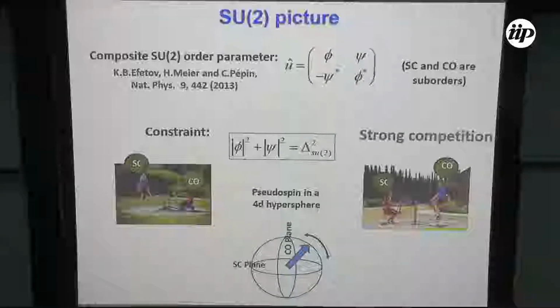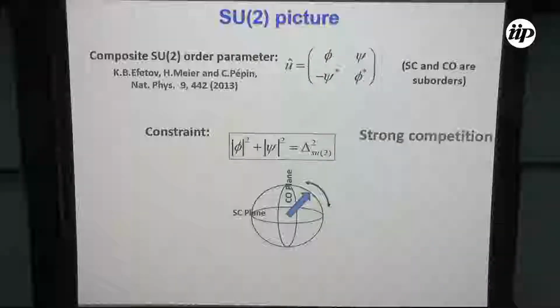We can represent this constraint by a pseudo-spin which lies in a four-dimensional space where we have a superconducting easy plane and a charge order easy plane, and this pseudo-spin can move around throughout this four-dimensional hypersphere. And this does not need any energy to move from one plane to the other because we have these equal energy contours. So what happens if we actually break the symmetry?